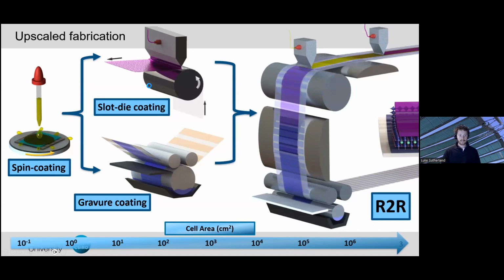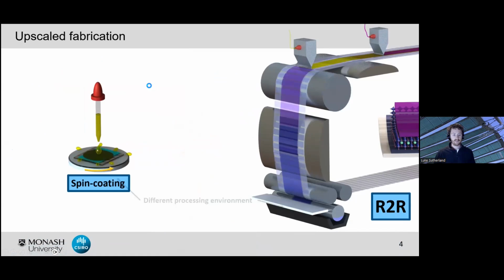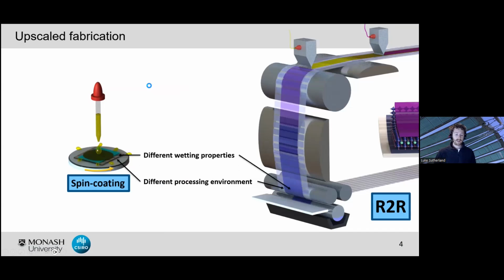However, this is much easier said than done. And so all along the way, we face a range of different challenges, starting from moving away from our highly controlled inert environment where we're fabricating these devices in our glove box without the risk of moisture and oxygen degradation. We're then moving towards our ambient lab environment where these molecules play a significant role. We then have different wetting properties between our glass substrate and our flexible PET, for instance. We also have strict annealing time limits and strict annealing temperature limits, which really play a significant influence on the crystallization of our perovskite layer as we're depositing this.